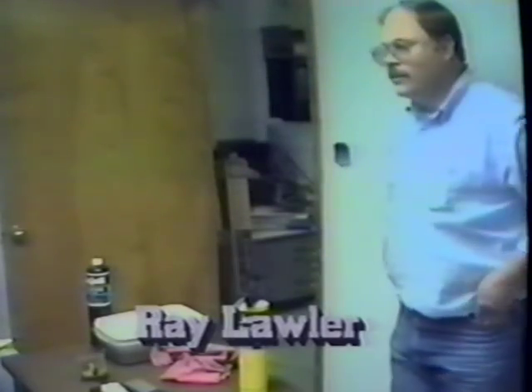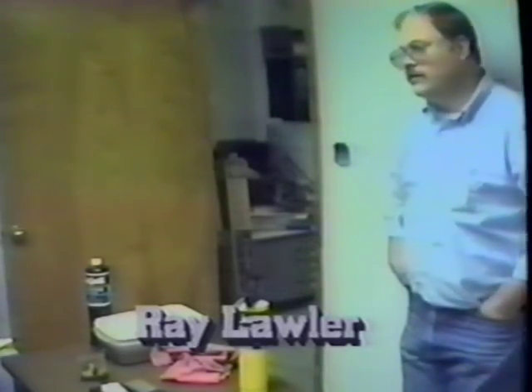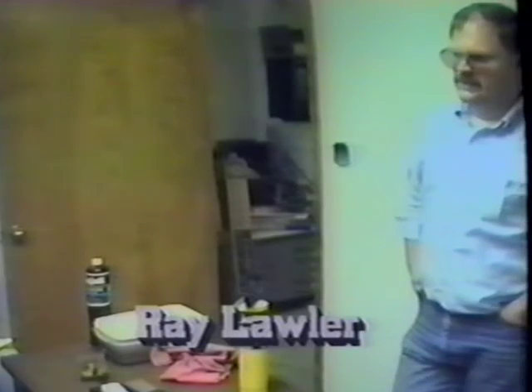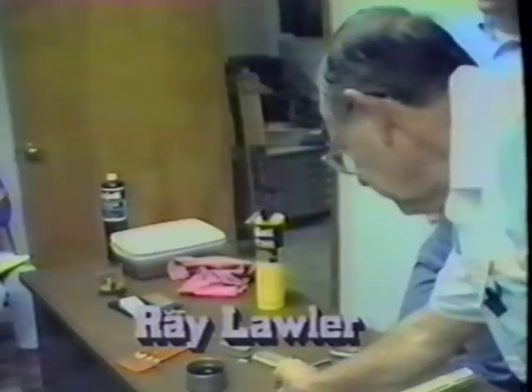Ray, is that hour's time just for that size tool? If you're doing thicker stuff, do you need to leave it in longer? We talked to our heat treater about this process, and that's what he said when we told him we were using 1/4 inch square, 3/8 square material. Normal drawing temperature is an hour per inch of thickness. So definitely the thicker it is, it's going to take more time for that temperature to soak the whole part, so it would take longer.